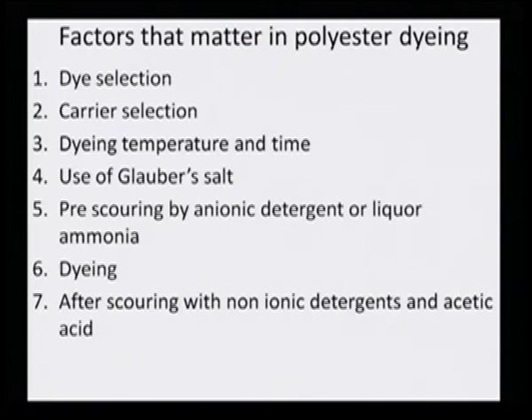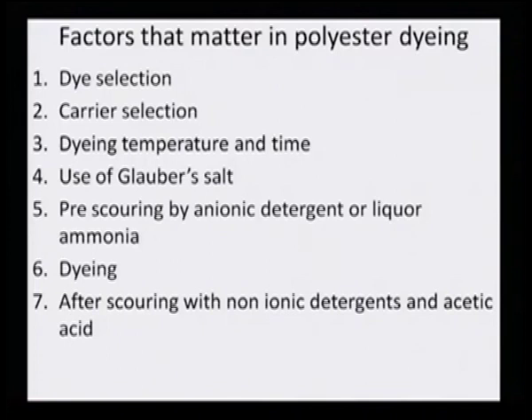Factors that matter in polyester dyeing are: dye selection, carrier selection if not following the thermosol process, dyeing temperature and time, use of Glauber's salt as a leveling agent, pre-scouring with anionic detergent or liquor ammonia, and finally dyeing after scouring with non-ionic detergent and acetic acid to fix the dyeing. These are the key factors to keep in mind when doing polyester dyeing.